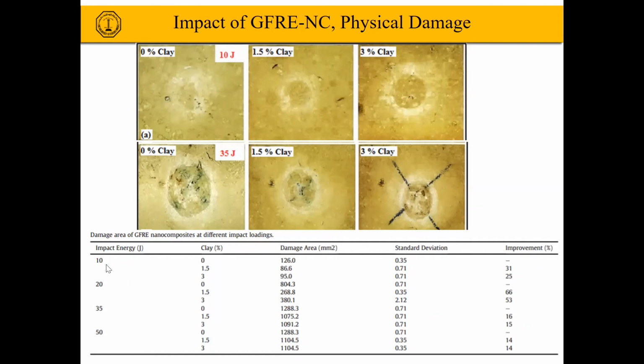These are the areas you can see for the impact energy of 10 joules, 1.5% of clay improves damage by 31%, 3% by 25%. Under 20 joules, we have even higher improvement, but at 35 joules, this is the threshold impact energy. After starting at 35 joules, we start having breaking or penetration of the top into the material.